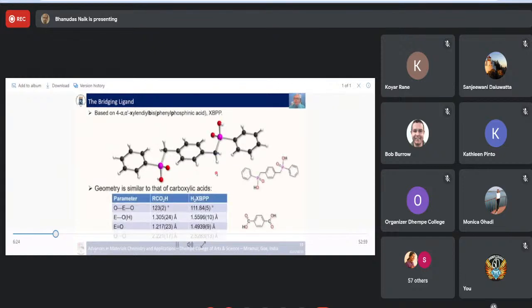A little bit more about the ligand compared to carboxylic acids. You can see that with this ligand, you must have another organic group here. The BDC, for example, only has the carboxylic groups at the ends, with the central organic part in the middle here, whereas this has a central organic part and also has to have this extra phenyl group here because phosphorus is 4-coordinate. The geometry is quite different.